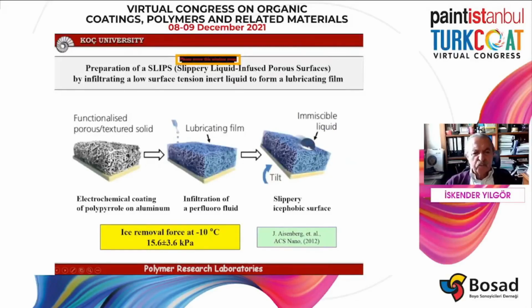But here, first you make a porous textured solid surface, a polymer. For example, in this case, they use polypyrrole on aluminum and they use electrochemical coating, which is quite complex. And then they filled it with either silicone type or fluoropolymer, fluoroliquid, just to make it hydrophobic. And then they said, this is slippery and icephobic, and it really gives very good properties.